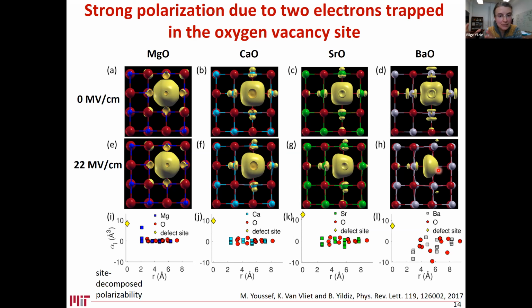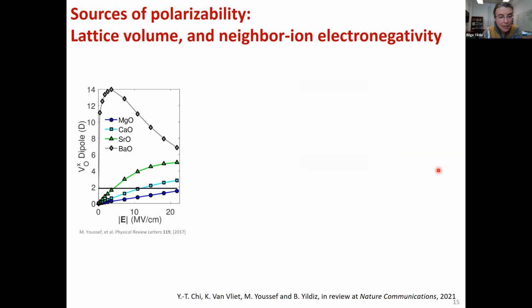All right, so we see this interesting polarization behavior, and we can observe from that work that the extent of polarization introduced in this non-polarizable bulk material, but polarized because of the defect, depends on the lattice constant of the material that we have examined. So going from magnesium to calcium to strontium to barium oxide, the net polarization increases, and that is positively correlated to the lattice parameter of the oxide. So that made us hypothesize that a key source of polarizability is perhaps the available volume for the electrons to polarize into.